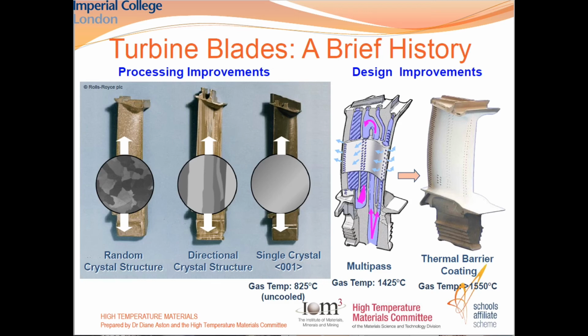So at the beginning, through processing improvements, at the beginning there were random crystal structures. So each blade had random grain orientations and a lot of weak spots. Then someone figured out that if you cool the melt from below, you can grow the grains upwards, and that's the second blade in. And you can see that in that case, the grain boundaries are still there, but there are none perpendicular to the blade. So none of them are in the preferred cracking direction, which removes one of the problems.